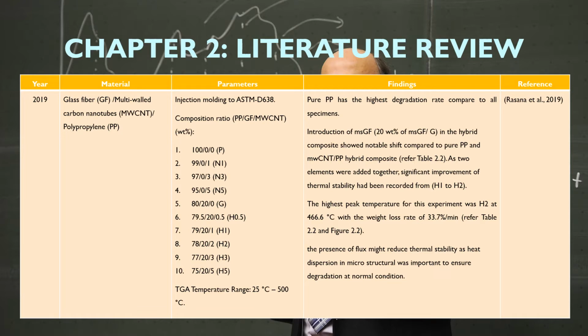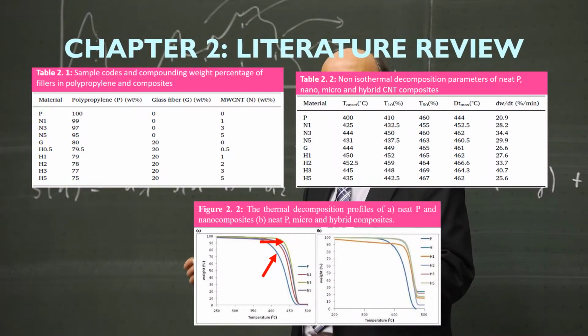Before we start the main discussion, there are several studies that have been done regarding this hybrid polymer composite. First was from Razana and her colleagues on the TGA result of PP, glass fiber and multi-wall carbon nanotubes polymer hybrid composite. In her findings, it was found that pure PP has the highest degradation rate compared to all specimens. Second, the introduction of glass fiber in the hybrid composite shows a notable shift compared to pure polypropylene and multi-wall CNT and PP hybrid composite. As two elements were added together, significant improvement of thermal stability was recorded from H1 to H2. This can be referred to in table 2.2.